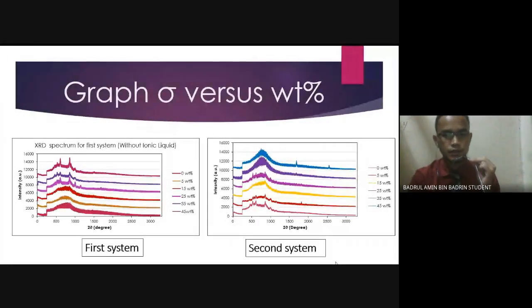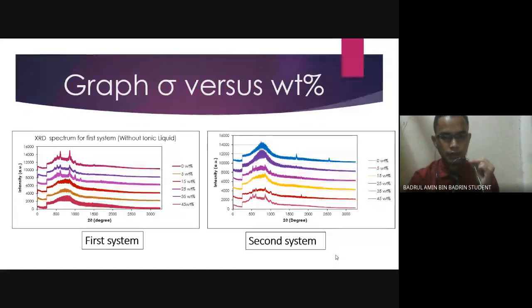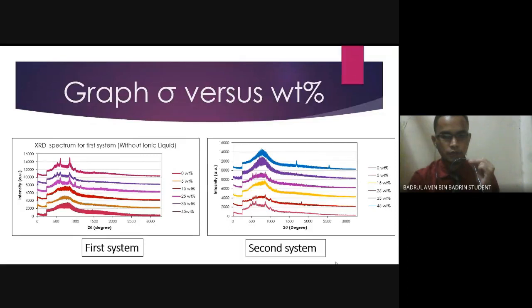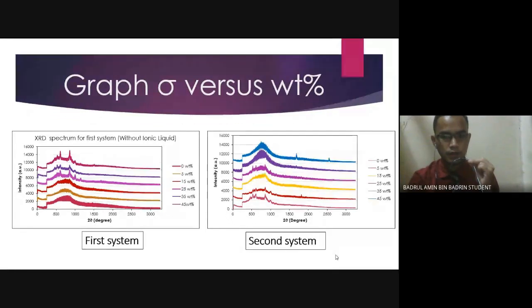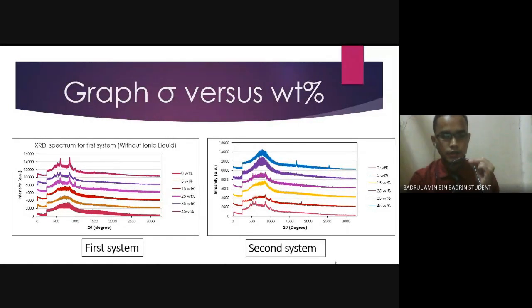So next is the third characterization, which is XRD, X-ray diffraction. This characterization focus on distinguish the difference between amorphous and crystalline phase in the samples. So the graph plotted between intensity and degree of Bragg's angle, we can see the broad area under the curve representing the amorphous phase. The wider the area under the curve, the more tendency of the sample to become amorphous. So when it is amorphous, it has high chances to become a better candidate with a high conductivity value.